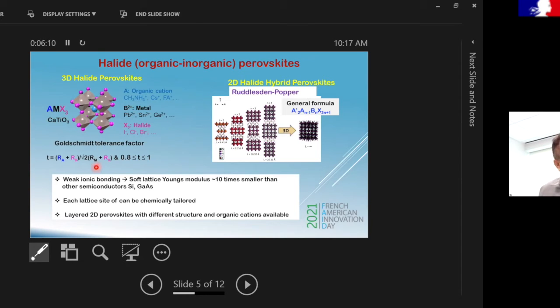And so if you mix all of this together and use this formula to predict what it is going to form, which is basically just the ratio of some ionic radii, if you get some value between 0.8 and 1, which means that you've made a perovskite material successfully. And so that's what this perovskite is, and it has some remarkable properties that I want to talk about.